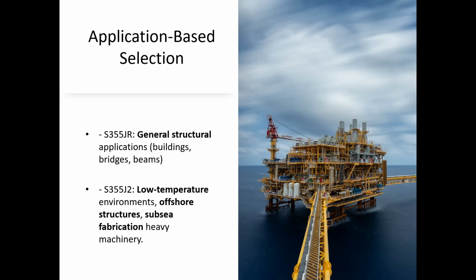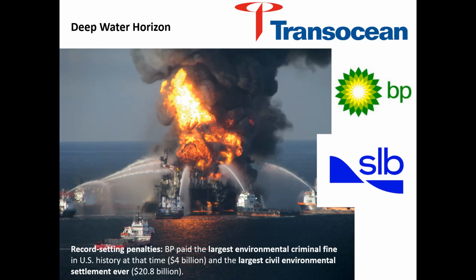So JR has its place, fitness for purpose, structural applications, bridges and beams that are not exposed to cold temperatures, whereas J2 is used for low temperature environments, offshore structures, subsea fabrication. The surface temperature of the water is not the same when you're going to do deep drilling. And that's very concerning if people are regrading JR to J2 for subsea fabrication when the temperature of the water at maybe 200 meters is going to be very different to the surface temperature. And this is definitely not what we want.